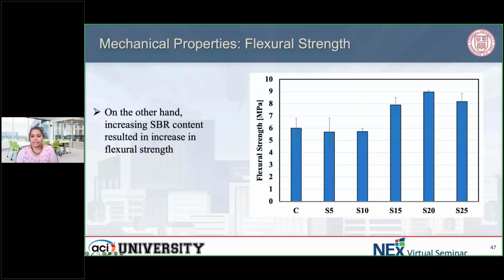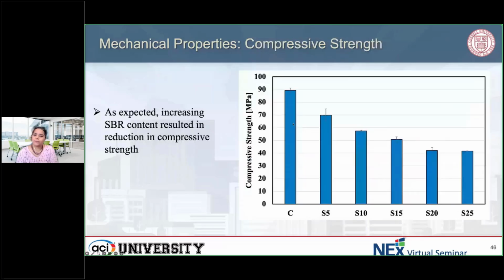So let's say here our control is like 6 megapascals for flexural strength and 90 megapascals for compressive strength. But then here, even though your compressive strength goes down to 40 megapascals, again, this is the whole point though. Like 40 megapascal is not a weak concrete. It's still good enough. We could just be over designing our concrete. For example, for the steps that we've printed in our lab, for the short span that we have, do we really need 10,000 psi concrete?